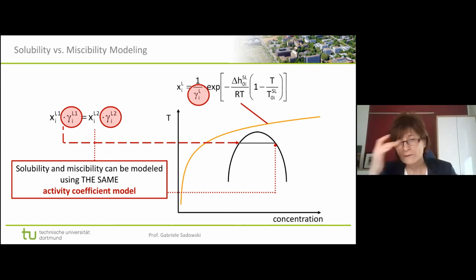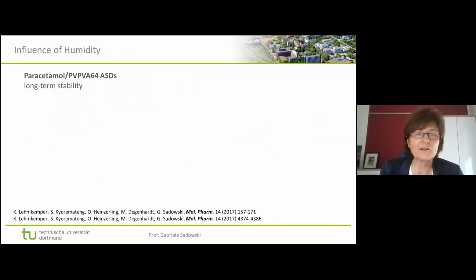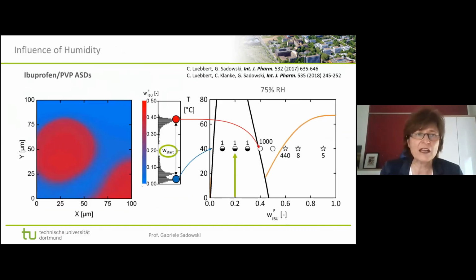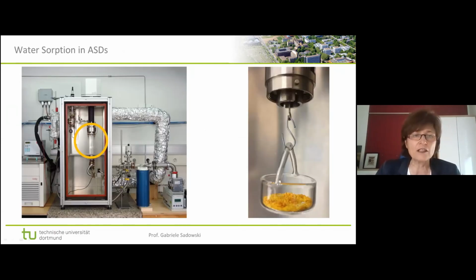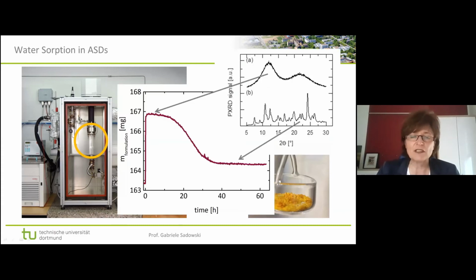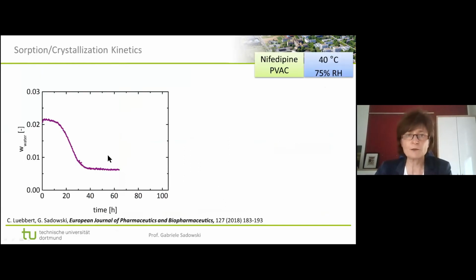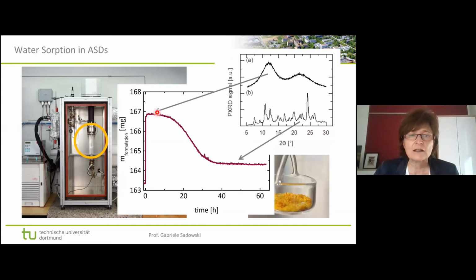So the last one from the same person, we had a lot of questions. In the sorption equipment, is the XRD measuring in line, I mean during the gravimetric measurement? Not in this one. In the meantime, we have actually four sorption measurements. This is the earliest one, and the PXRD is not in line. So for the measurements I have shown you here, we really took samples. So we have repeated this particular measurement. We really opened this cell here, which actually finishes the measurement. We opened it, took the sample out, and then made a PXRD. And then we started with a twin sample, the measurement again from the beginning to the end, and took the sample at the very end.